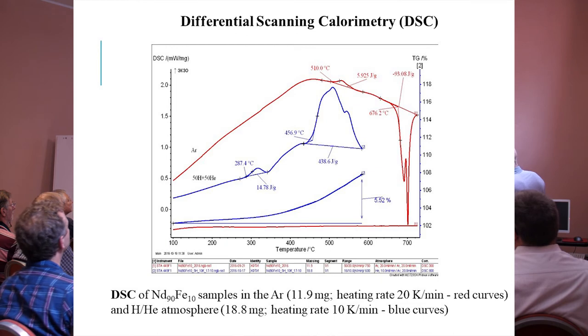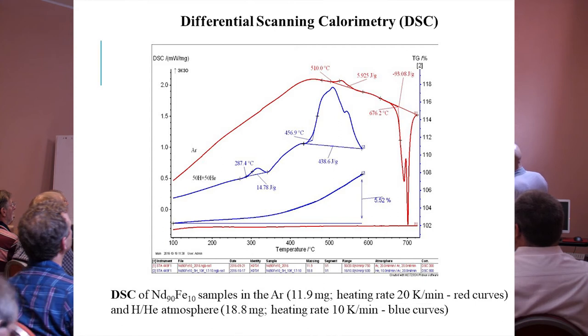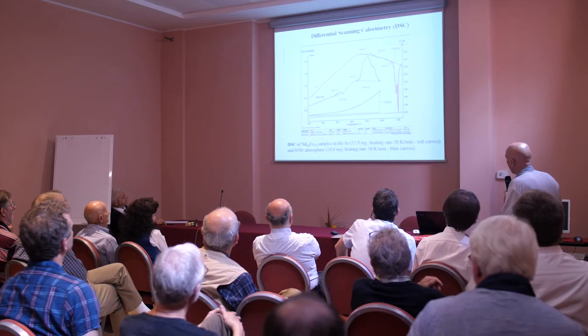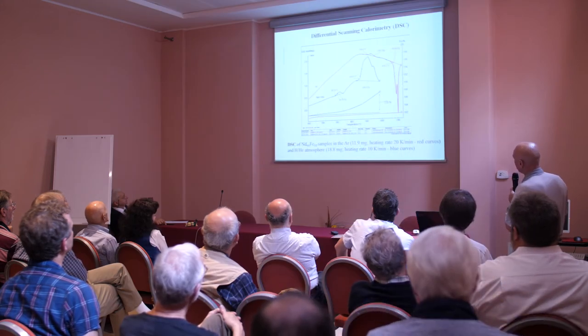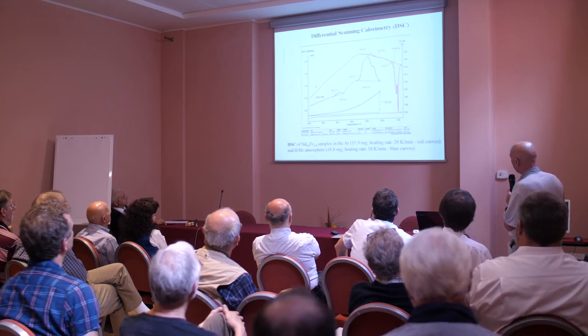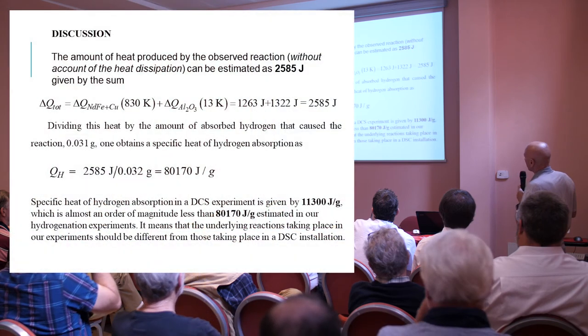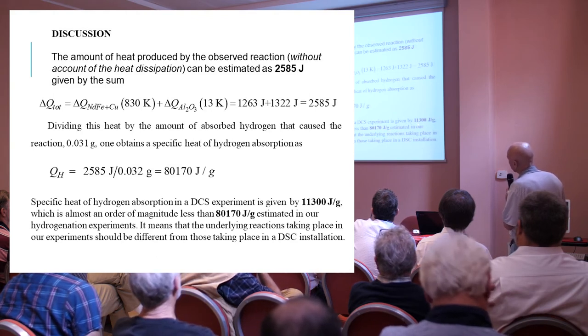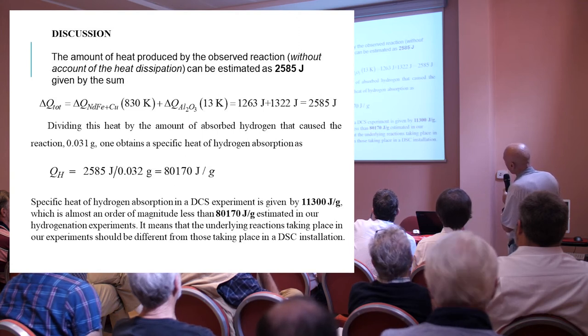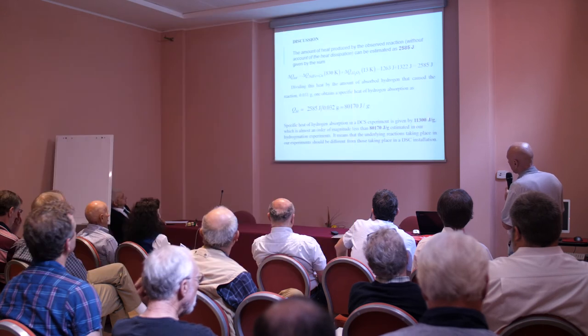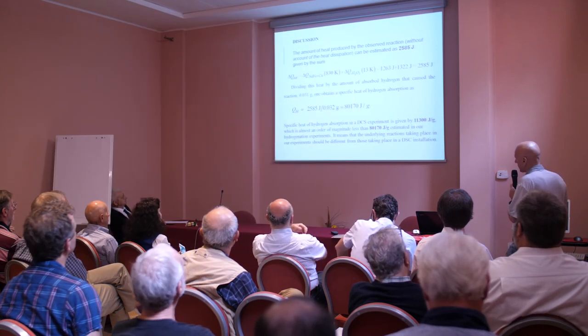What is surprising is that we tried the same material to analyze in the differential scanning calorimeter. And here in the argon atmosphere, you can see, for instance, the heat of amorphous to crystalline conversion is negligibly small. So it can be explained by this. And also, you see the experiment in a hydrogen flow. And you may calculate the heat produced. And then when you compare these two figures, you find that in this big experiment, let's say, we produced almost 80 kilojoules per gram of hydrogen, while in the DSC experiment it was 11. So 8 times more was produced here. It's an estimate, of course, but